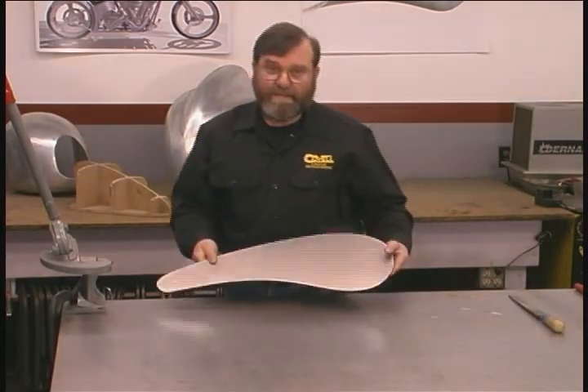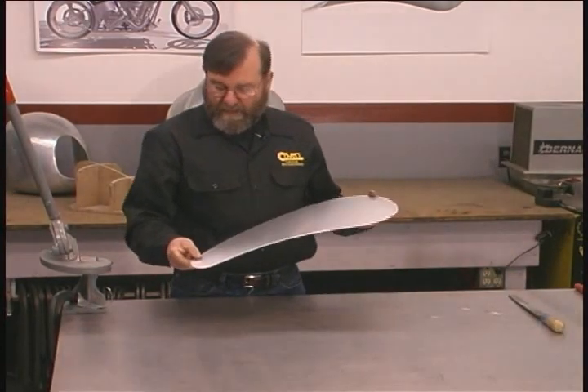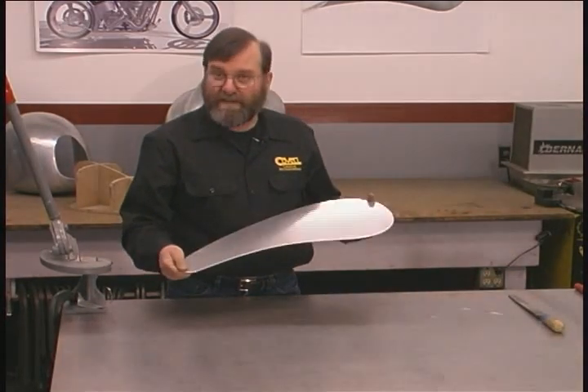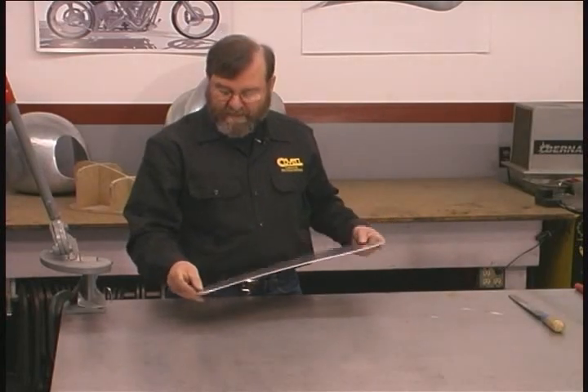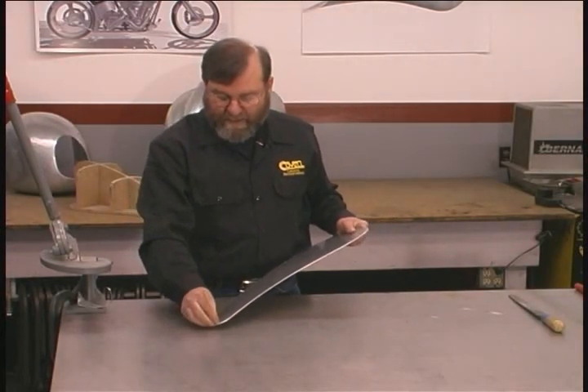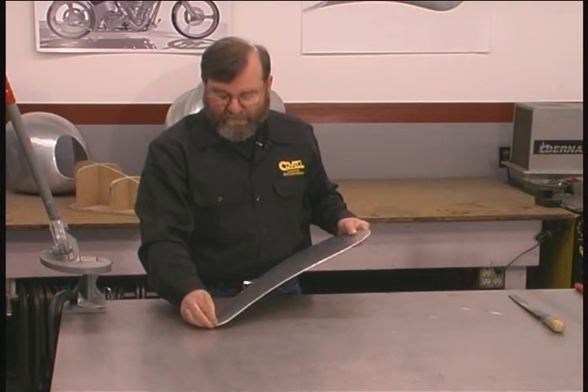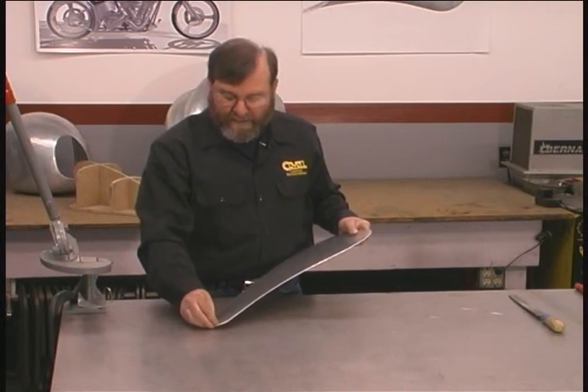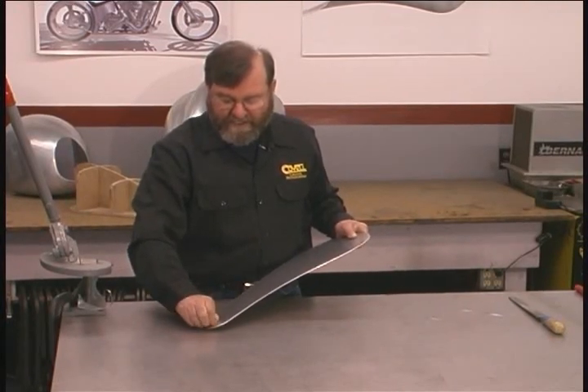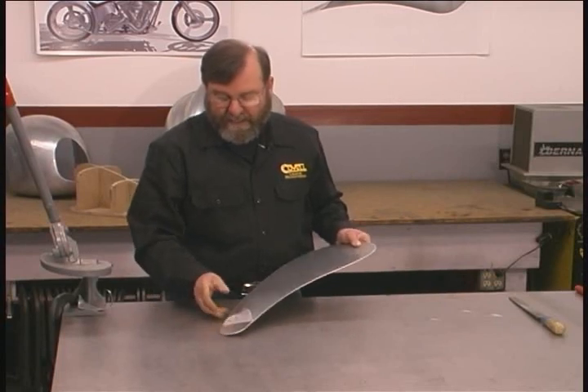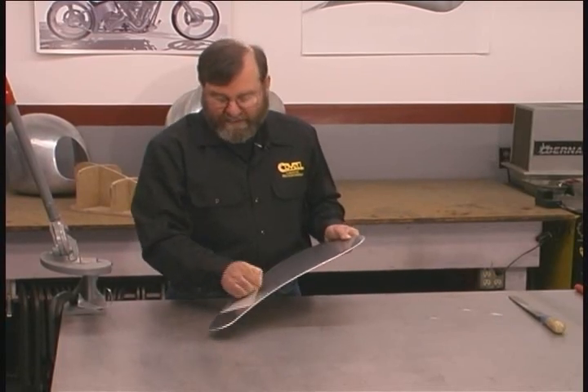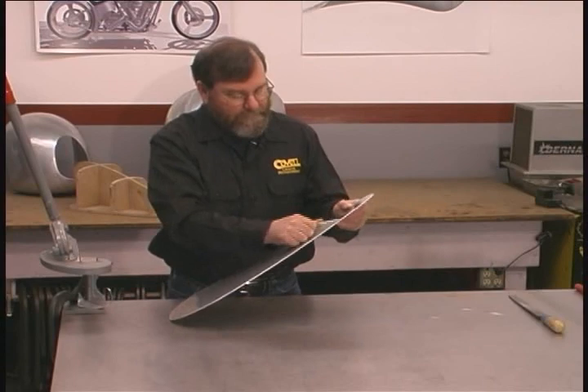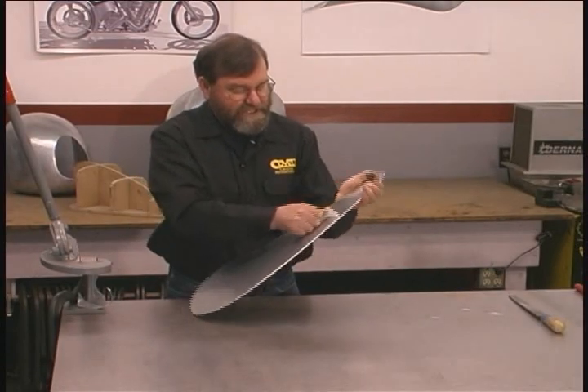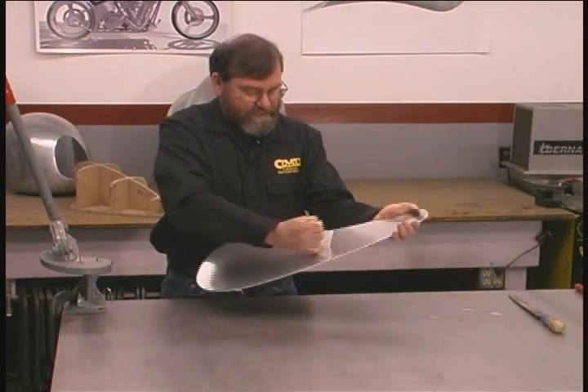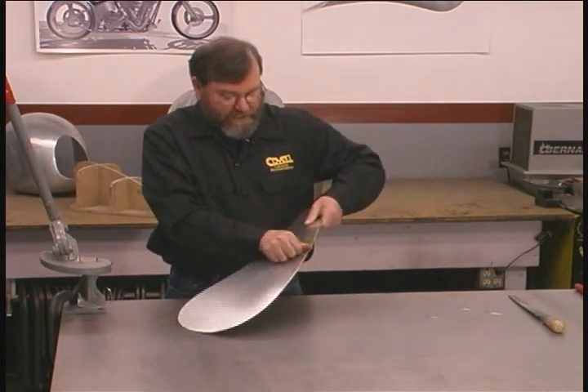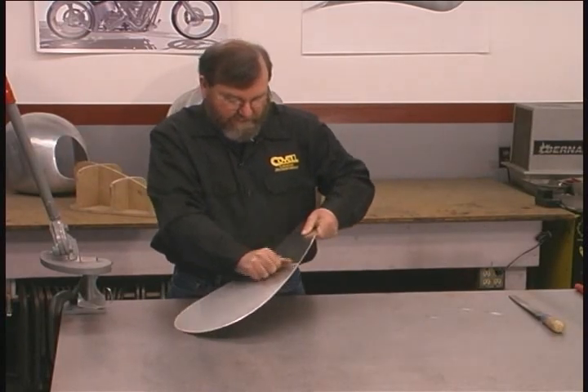Okay, our part is deburred. When I buy this material, I specify that one side of it be covered with a PVC plastic. And this goes a long way toward preserving the finish of the material. Aluminum is very soft and scratches easily. But we're going to be heating this piece of aluminum to anneal it or soften it. So I need to remove the plastic sheet to prevent it from burning during the annealing operation.